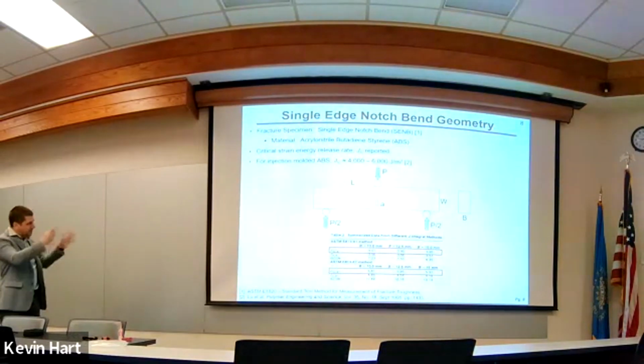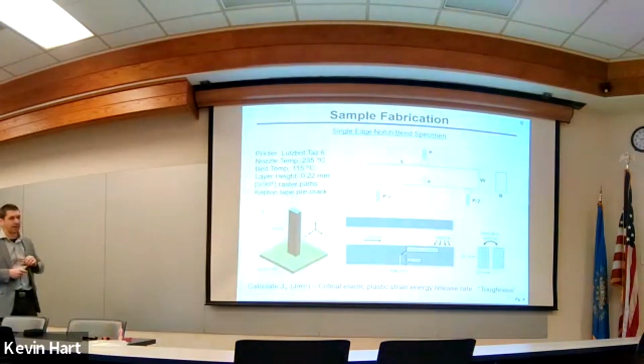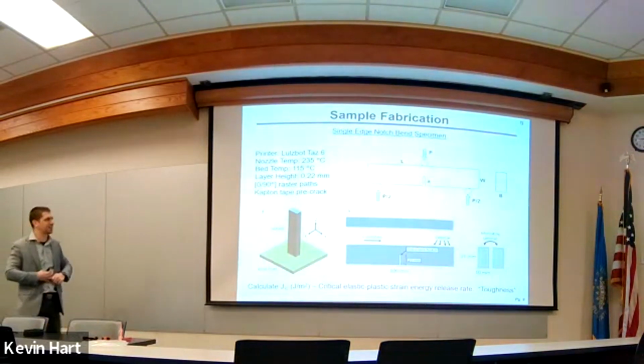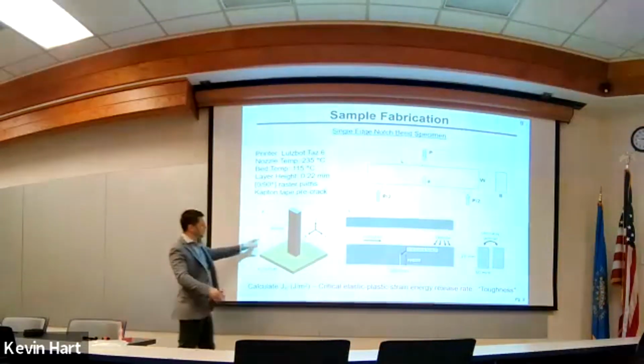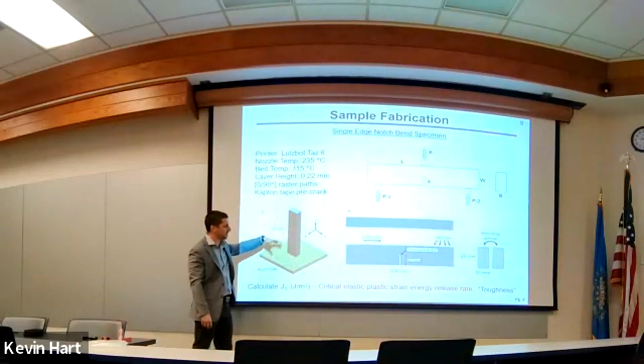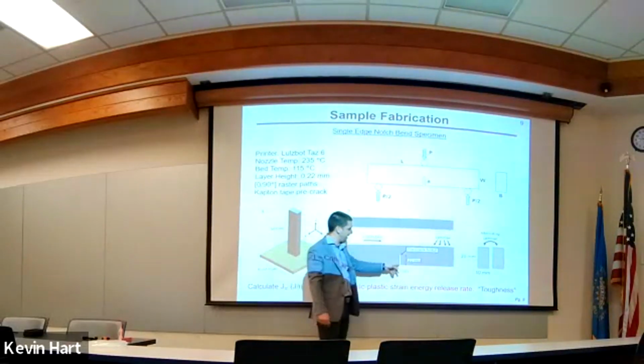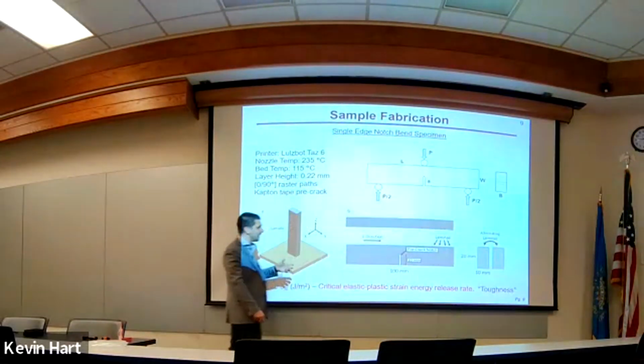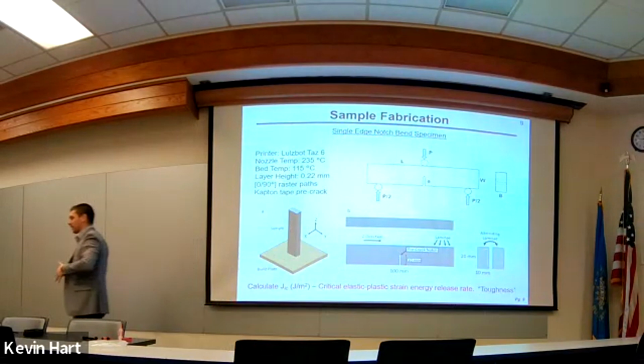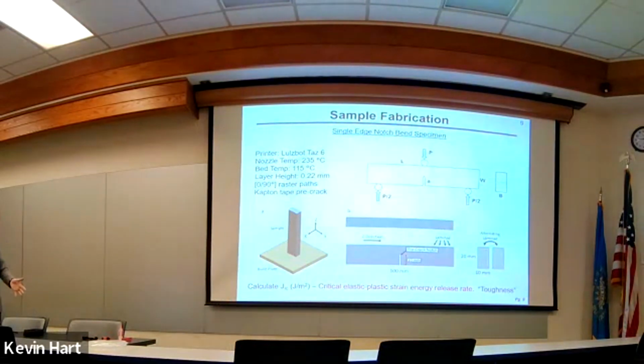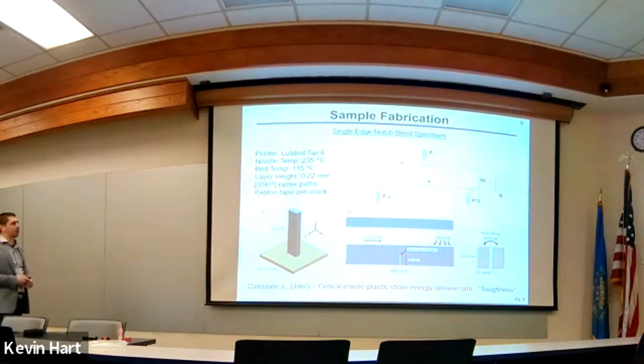All right, so now we take that idea. This is for an injection molded sample, but I want to do this with a 3D printer and test the interlayer strength between the layers of the 3D printed sample. So we build this rectangular prism, the single edge notch bend specimen. We put in a pre-crack inside of the sample, between two of the layers, in the middle of the print. And now we're going to test this in 3-point bend and evaluate its critical strain energy release rate, and compare that to an injection molded sample.